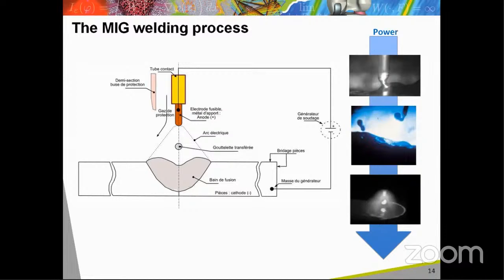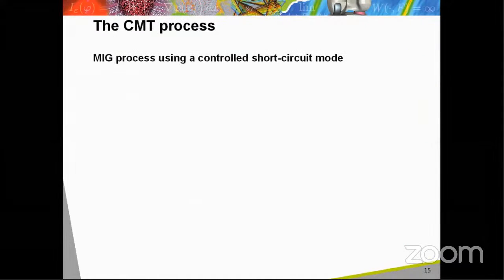Finally, when the arc power is higher, the liquid droplets are smaller and more regular and are sprayed axially, producing a regular deposit. This transfer regime is called the axial spray mode. The axial spray mode produces also a strong heating of the produced samples that can require the cooling of the component and a delay before proceeding with the manufacturing. For this reason, the short circuit mode is preferred for additive manufacturing with the WAM process based on the MIG arc welding process. The CMT process has been developed by the Fronius company to improve the regularity and the stability of the deposit obtained with the MIG process in short circuit mode.